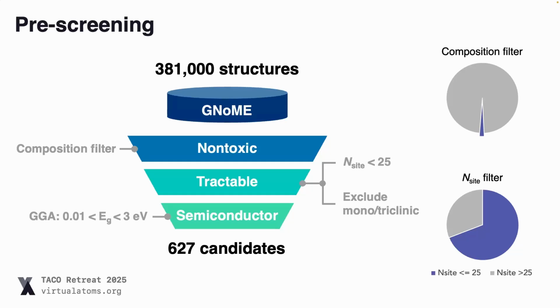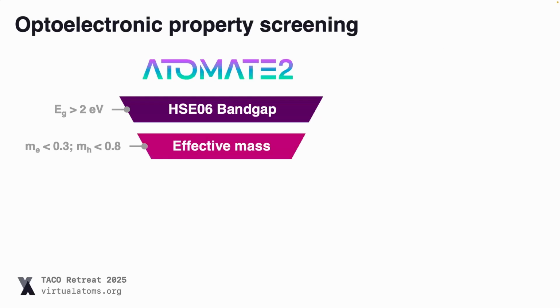And the last thing is we filtered them based on their calculated GGA band gap, just to make sure that they were semiconducting, because that's what we're interested in. We're interested in a very wide band gap material, so I think it really needs to be semiconducting at the GGA level. And this actually eliminated almost all of the candidates, and we got to 627 materials. The next thing we did is calculate their band gaps using HSE06.